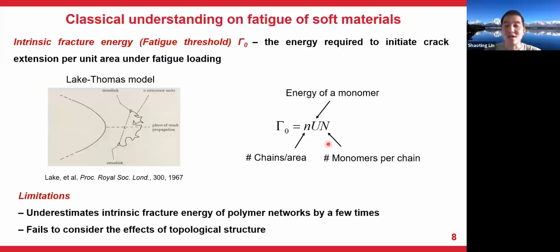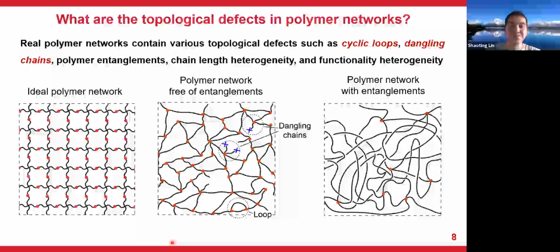But recent studies manifest several limitations of this model. First of all, the Lake-Thomas model underestimates the intrinsic fracture energy by a few times, and currently there's no model to theoretically explain this underestimation yet. And second, the Lake-Thomas model does not consider the effect of topological defects, which are inevitably present in real polymer networks. And real polymer networks contain various topological defects such as cyclic loops, dangling chains, polymer entanglements, chain length heterogeneity, and functionality heterogeneity.